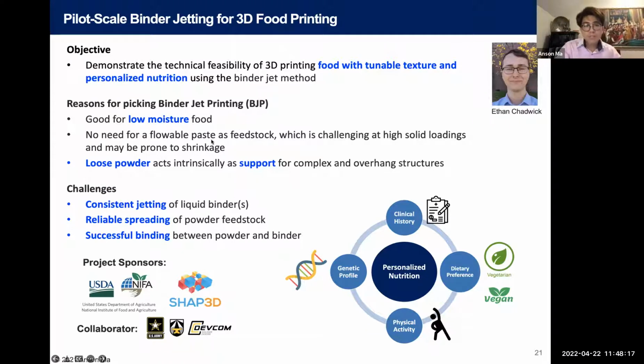And we picked binder jet printing. There are a couple of reasons: it's very suitable for making low moisture products, and it doesn't have to formulate a paste, which could be problematic. Sometimes you cannot formulate a paste that is printable. With binder jet, you don't have this problem because you're dealing with the powder and the ink separately.